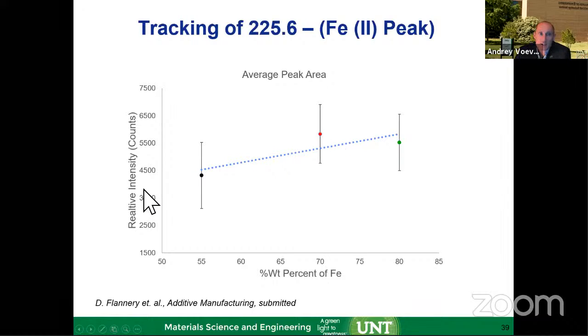We can see that the intensity, or relative intensity, of the peak after correcting for the background is also trending higher. However, we also see a lot of data scattering. You can see here the huge data scattering. This is due to uncertainty of background correction, uncertainty of the peak location, and uncertainty of overlap. So these are the challenges with our spectroscopy additive manufacturing method, that we need to find the algorithms and ways to reduce these uncertainties and make the error bars much smaller. The trend is there, but it is not yet very usable, I would say, at this point, for any process control or looping until we reduce the scatter of the data in spectroscopy.